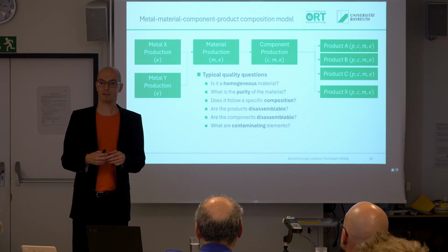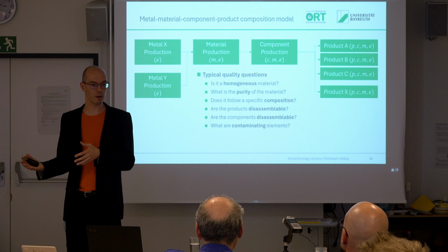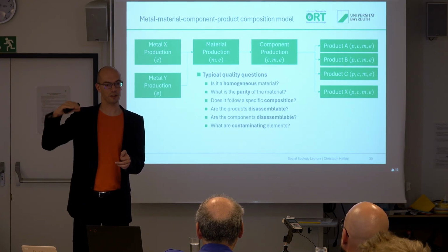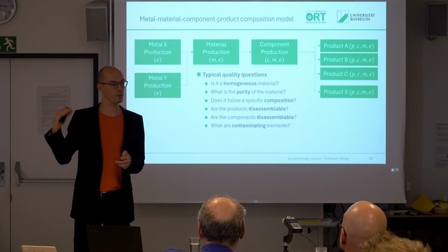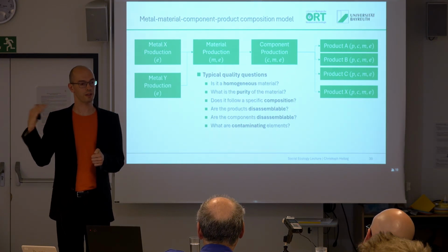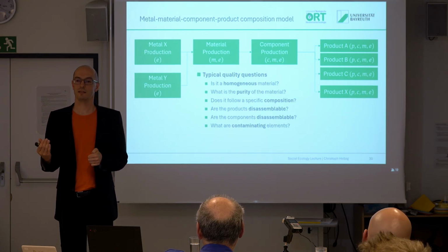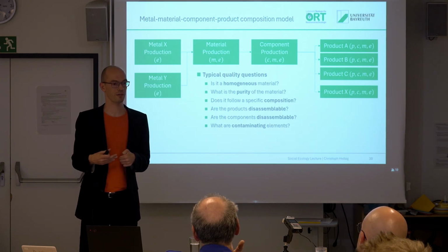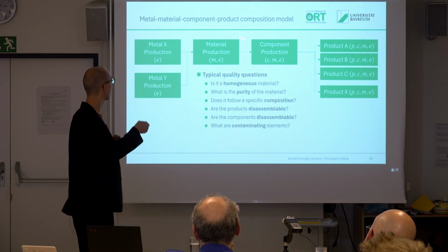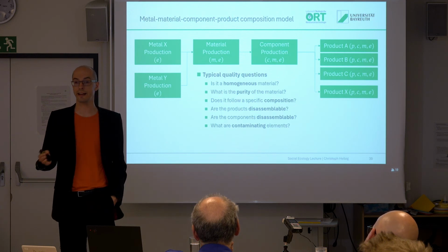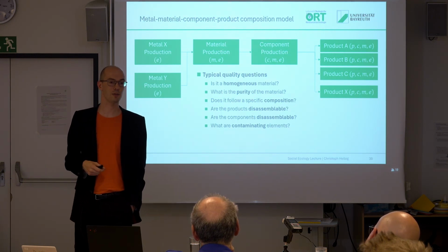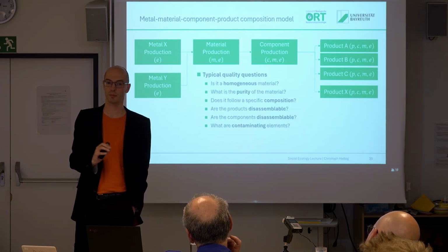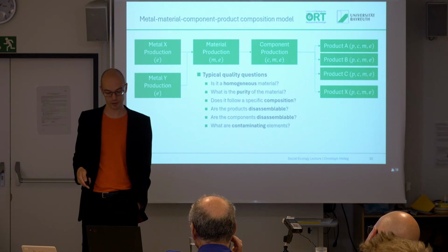So, for example, copper in steel is an issue. Copper content in steel is rising in Europe and in Asia and in the US, everywhere, and becomes an issue for steel recycling. But of course, copper contamination is not an issue for aluminum that much. So we need to be very specific about what kind of material we are talking about. Steel and aluminum are both used in cars. So it's not about copper in cars, it's about copper in specific materials.